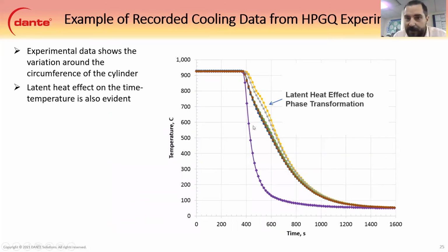And this is kind of what the data you would see. You see this purple line here. It quenches really fast, so that would be indicative of a surface thermocouple here. These ones will be closer to the core, and then closest to the core we would have these ones. And you see there's a little bump in the time temperature data here. This is because of latent heat. There's a phase transformation going on. Based on the temperature, it's probably ferrite or pearlite, or maybe very close to upper bainite, but you know.